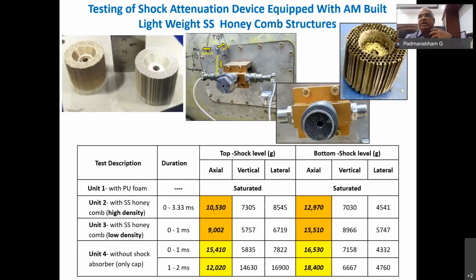Next one was a honeycomb kind of a structure with, you can see that porous structure, the vertical channels, and this should have a particular shock attenuation property. This also is used in certain missile applications. So when something comes and hits, it should get collapsed and absorb the impact energy. So depending on the shape of these channels, the wall thickness, the shock attenuation capabilities will change. So depending on the user requirement, these channels were designed and built, and you can see the actual experimental design that the desired shock attenuation has been achieved.